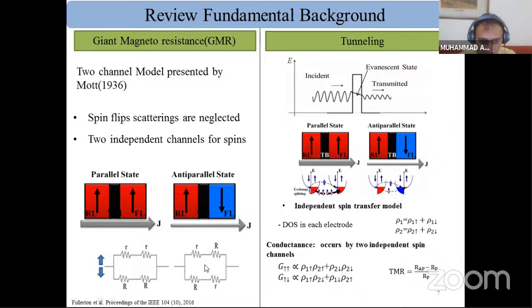I will explain this in a two resistor model. This arrow represents a spin up electron, and this arrow represents a spin down electron. You can see for a spin up electron, there is a low resistance state. Here, high current flows through the spin valve. For an anti-parallel state, here is the reference layer and the free layer. There is an anti-parallel configuration.